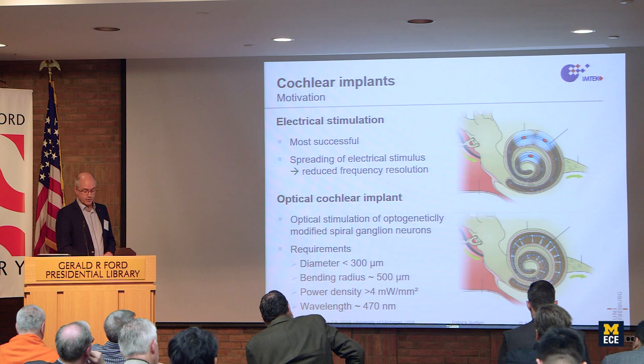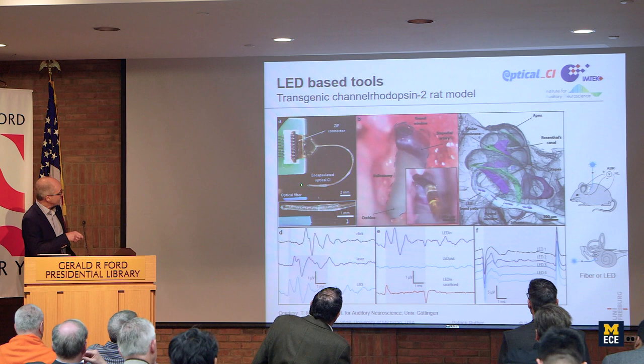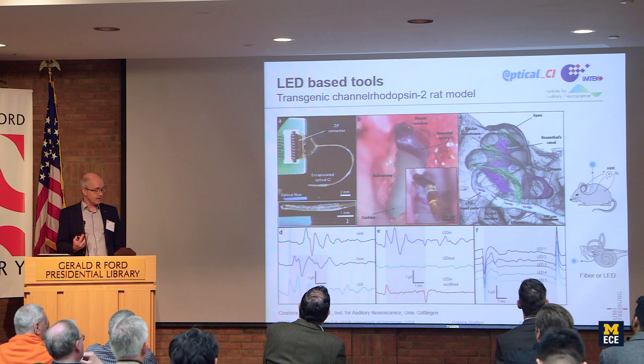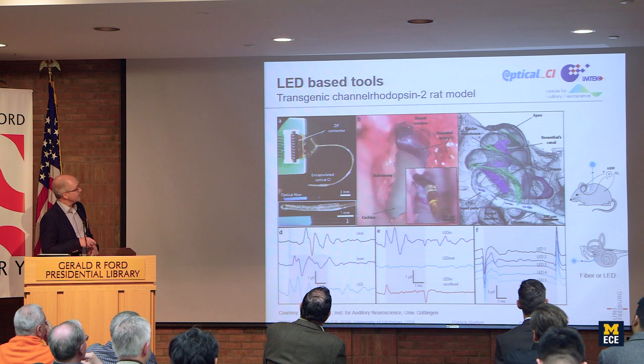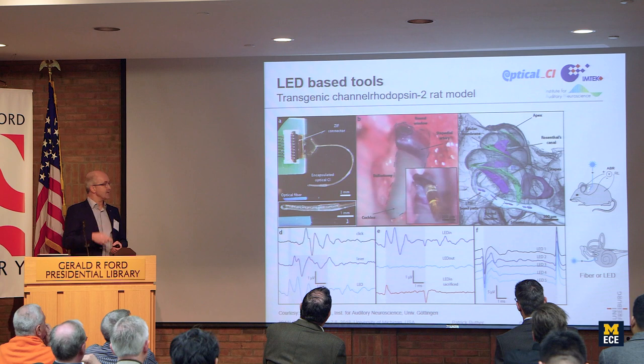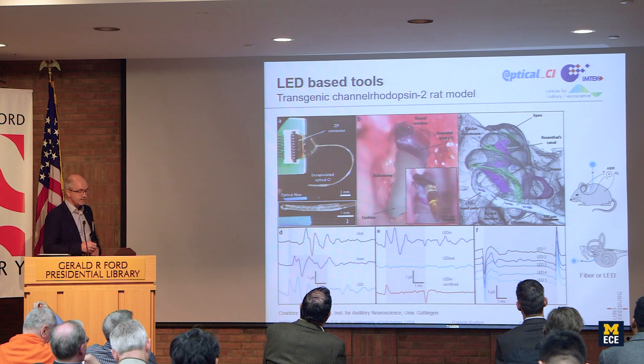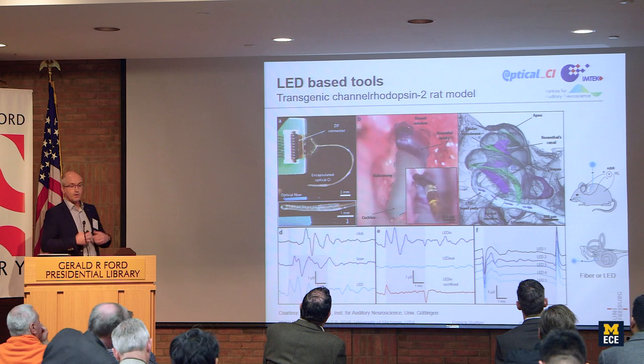Now, using the probe that Michael did, meaning micro-LED chips on a flexible substrate, as shown here, we implanted, or better to say, our colleagues in Göttingen implanted these probes through the round window into the cochlea. And what you see here with this MR image, you see how the probe winds inside the cochlea. You can see the contact pads where the LEDs are. And we stimulated the cochlea with light pulses from these implanted LEDs.